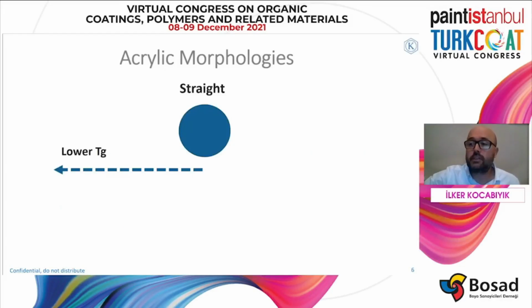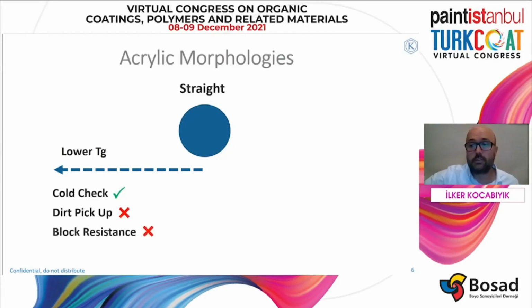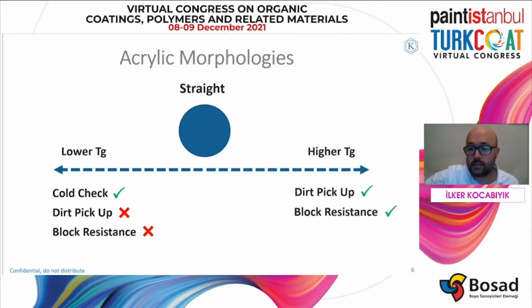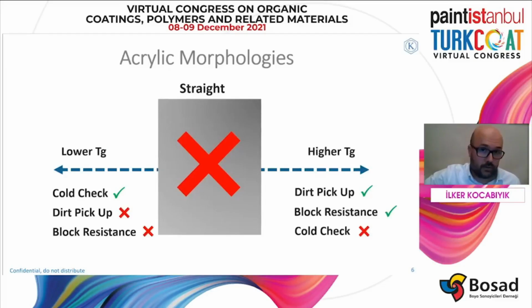Elasticity of acrylic emulsions is related to glass transition temperature (Tg) values. Acrylic emulsions with straight morphology can be designed with high or low Tg according to monomer selection. It is a well-known fact that low Tg polymers will give flexible dry films, which is definitely good for high cold check performance, but worse for dirt pickup and block resistance due to dry film tack. Increasing Tg value could be a solution to avoid surface tack and achieve enough dirt pickup resistance and block resistance. But this time, we will lose elasticity and cause failure in cold check resistance. So straight acrylic morphology doesn't seem to be the right option for an acrylic binder for exterior wood.